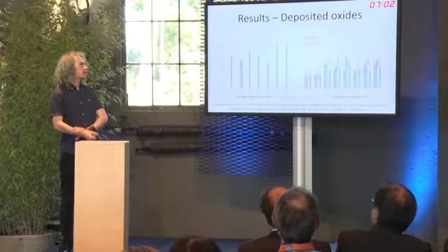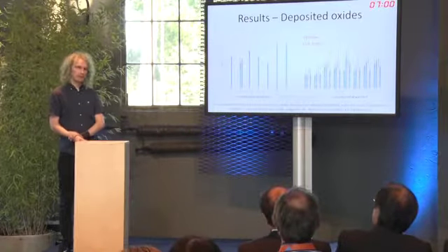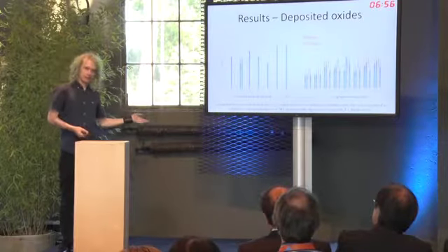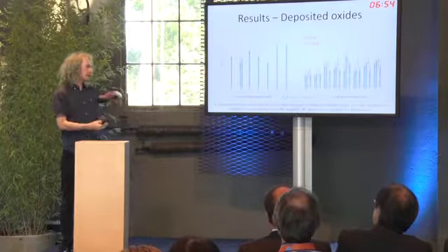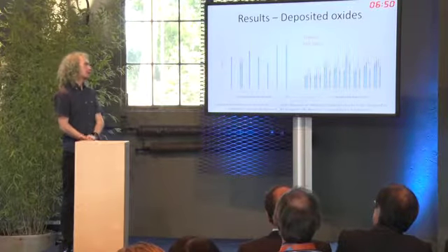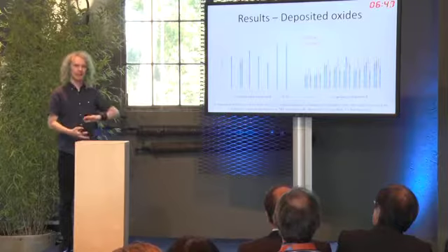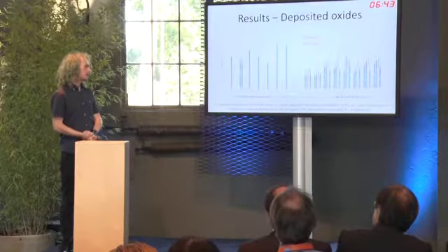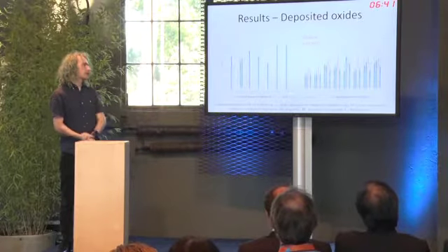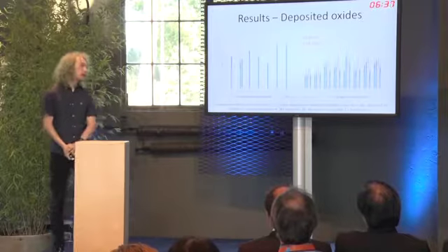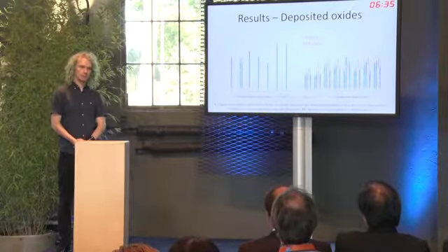Now, coming back to the oxides that we deposited individually on there, we tried them out with this method. We used distilled water to deposit them in a solution and then let that dry out. However, these results, we don't necessarily trust them simply because it varied the degree of oxidation of the surface. Unfortunately, we couldn't really find a great deal out from that. The isopropanol we also used as a solution to deposit the oxides, and there we got a much more stable result.